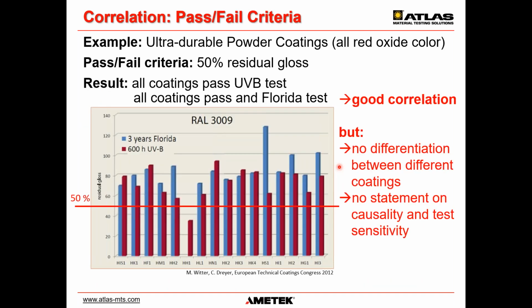But sometimes you even find publications claiming correlation where all materials actually pass the tests and no materials fail the test. There is one material shown here in the middle, which actually is below the pass-fail criteria in this study, but here the outdoor weathering counterpart was lost or not considered in the study, so this could not be considered. In this example, ultra-durable powder coatings in a brownish red oxide color have been exposed, so different formulations have been exposed to Florida for 3 years and even longer, and to UVB weathering for 600 hours. So it's a very comprehensive study where this is taken from.